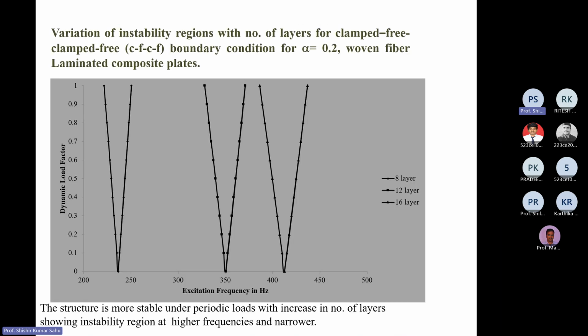This is the wedge-shaped dynamic instability curves. This is the zones of instability. This is the zones of stability. This is done based on the dynamic stability formulation, harmonic loading, for different layers: 8 layer, 12 layer, 16 layer. This is for 16 layer. This is for 12 layer. This is for 8 layer. As you can see, the excitation frequency is higher for 16 layer than 8 layer.